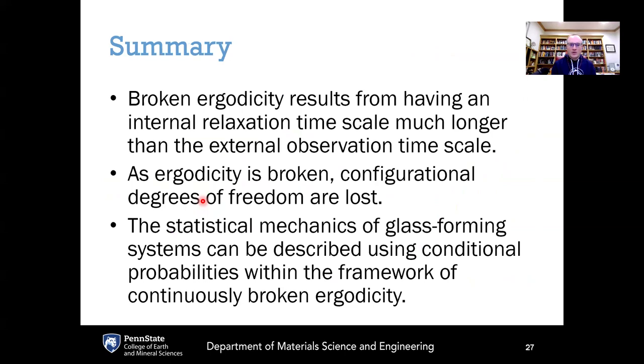To summarize: broken ergodicity results from having an internal relaxation timescale much longer than the external observation timescale. As ergodicity is broken, configurational degrees of freedom are lost, and their contributions to thermodynamic and statistical mechanical properties are lost. In the most general sense, this can be described using conditional probabilities within the framework of continuously broken ergodicity. Thank you very much for watching, and I will see you next time.